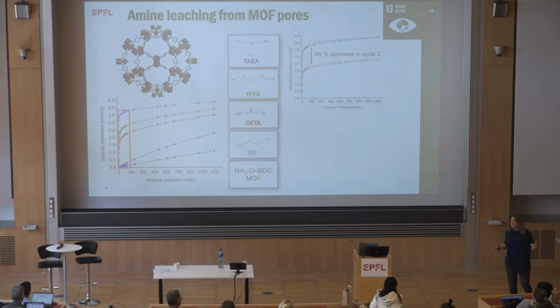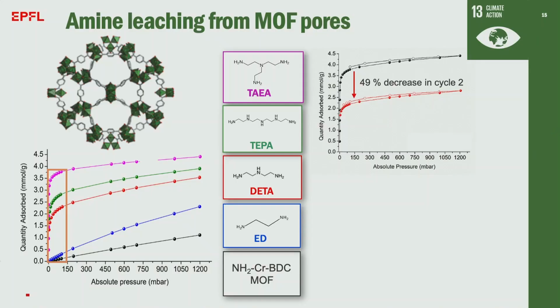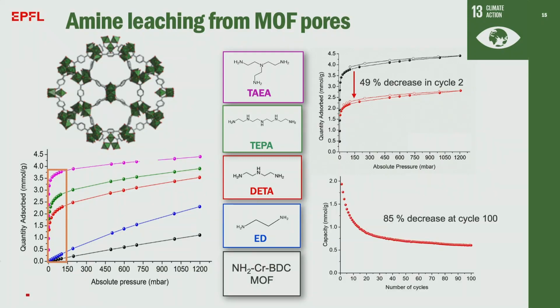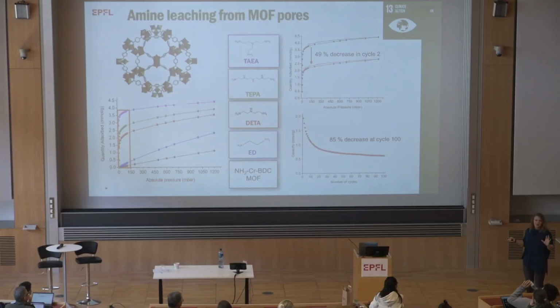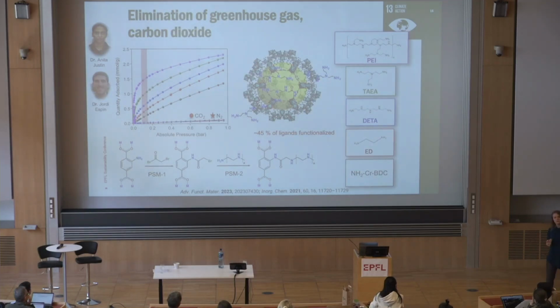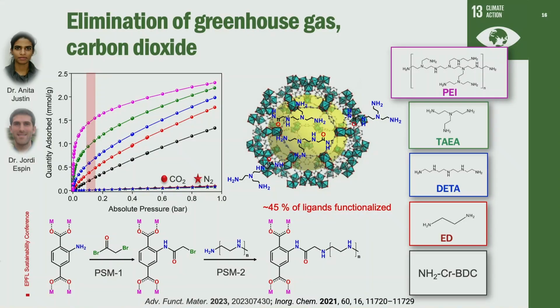Well, this is great, but what's the problem? Well, we only get good results for our first measurement. So after we release that CO2 and do another measurement, we see that our capacity drops by 50%. When we continue cycling the material, we see effectively that it's dropped by 85% just in 100 cycles. We need to be able to cycle these things thousands and thousands and thousands of times. So the key is that basically our amines are flying out of the pores. This is the problem. And so as chemists, what we decided to do was go in and see if we could immobilize those amines inside.